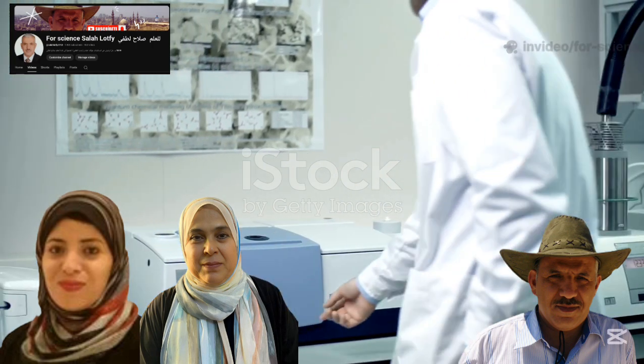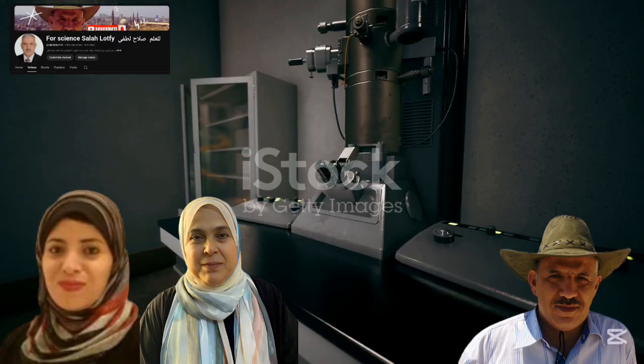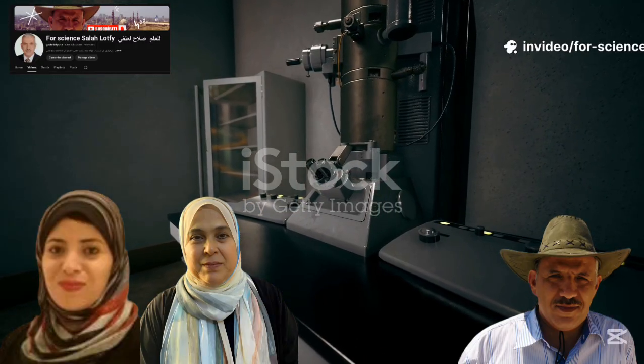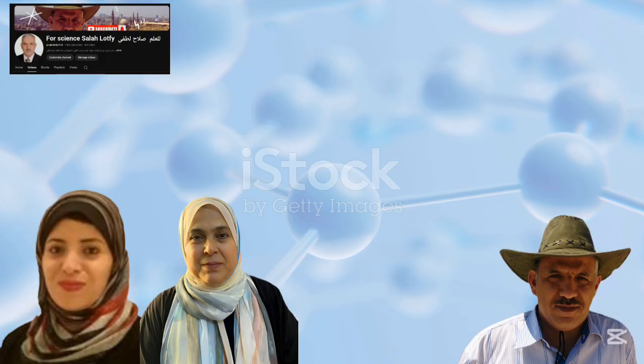To probe structural changes at the atomic level, the team used electron spin resonance, ESR. ESR is highly sensitive to free radicals created by ionizing radiation. Surprisingly, after 250 kGy gamma irradiation, the spectra of all three glasses showed no sharp ESR signals. This means that almost no free radicals were formed. The glass networks resisted radiation damage. The minor asymmetry between spectra was simply due to differences in ion composition. The conclusion was clear. These glasses form a highly stable blocked network where radiation photons lose energy without creating defects. This is exactly what we want in a shielding material.